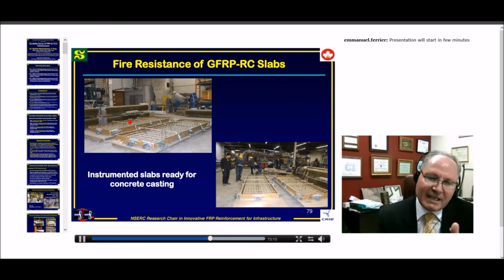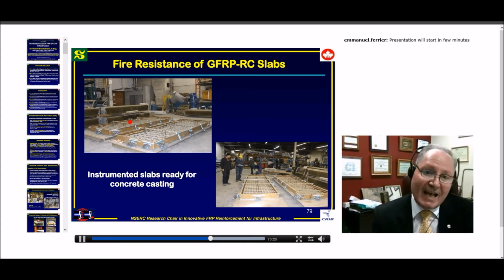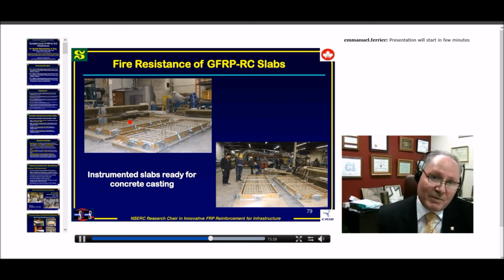So the time rating that we use for buildings in the Canadian building code is 2 hours. But we did not have any test results. When we developed the S806 code in 2012, I was one of the people responsible for the clauses regarding fire resistance, because, as I showed you with a couple of parking garages, when we did these parking garages, we specified a concrete cover of 60 millimeters, and at that time we said we hoped that in the future we could do some tests and maybe this concrete cover could be revised.